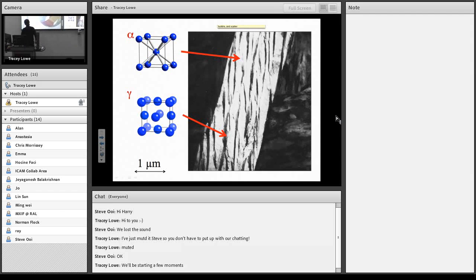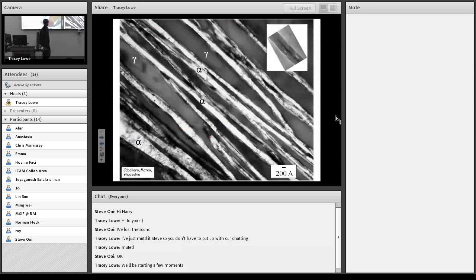But watch this next micrograph. Are you ready to see this next micrograph? This is something that I really like to show many times. This is the world's first bulk nanostructured material. There is nothing to match this. We can make it in thousands and thousands of tons. Indeed, it is made in thousands of tons, where the plates are actually finer than carbon nanotubes. But this is incredibly strong stuff. It's more than 2,000 megapascal strong. So it will have all kinds of problems with hydrogen, we imagine.